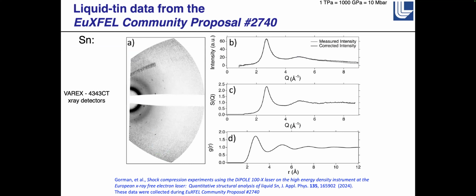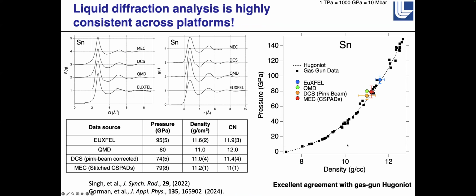This shows tin data that we took at the European XFEL, and the analysis that we did. This is the intensity, this is S of Q, and this is G of R that we obtained from that analysis. We've also done it at MEC at the LCLS at Stanford, and at DCS at the Advanced Photon Source, and this shows data from all of them, including a QMD simulation. It shows that we basically get the same G of R and the same S of Q when we do this analysis, and the densities are shown here at comparable pressures.